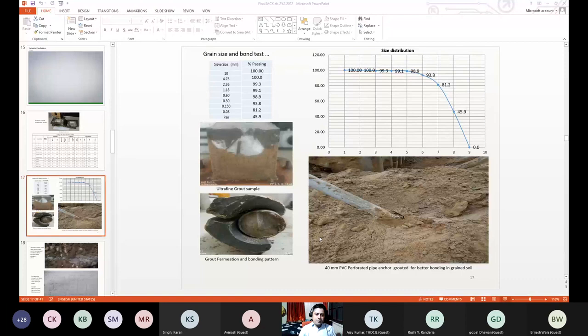The procedure is the spacing between two adjacent injection ports shall be 1000 mm center to center for fixing injection packer for port drill hole of 12 mm diameter and to a depth of 150 to 200 mm using a suitable drill machine. You can do it, and the pressure is to be maintained up to 2 to 5 bar, not more than that, because your concrete may crack. It is again another challenge. So you have to keep optimum pressure.